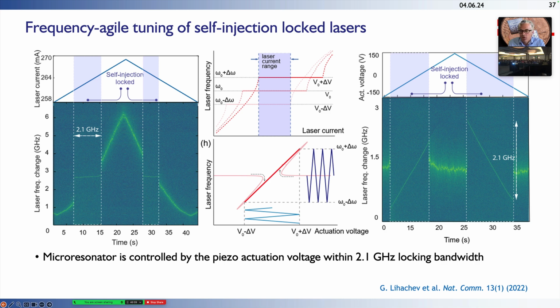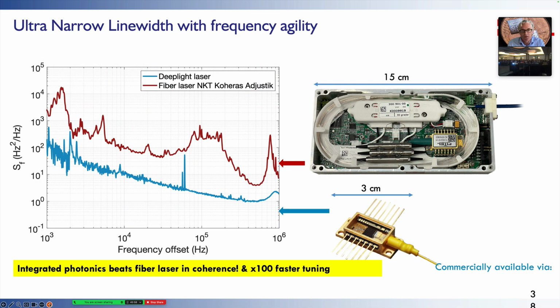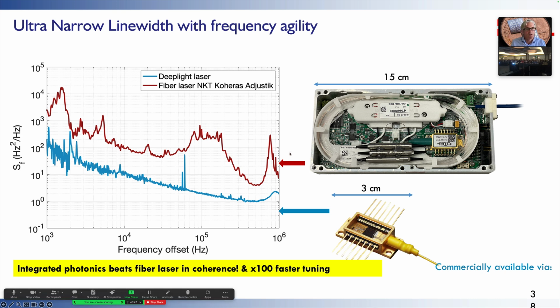But importantly, due to the use of AlN as an actuator, we can have a bandwidth that is very substantial, typically much more than the few tens of kilohertz that bulk piezoelectric lasers would tune. Let's take a look at how well these devices perform. One of the first results we obtained was looking at the laser linewidth of these frequency agile low noise lasers. And we compare it to the fiber laser, which is a workhorse for optical fiber sensing.